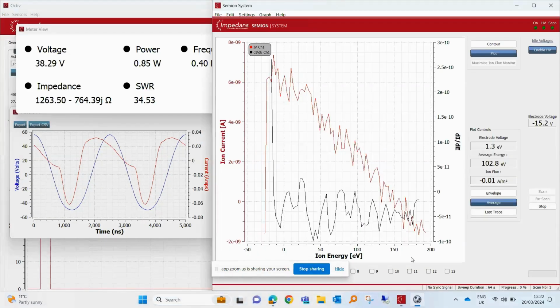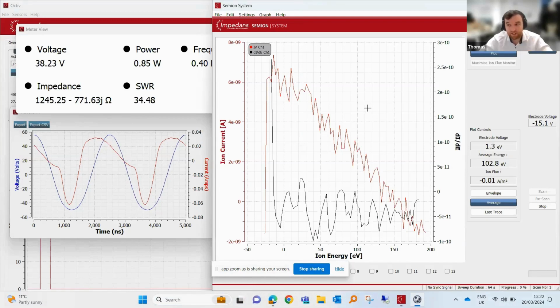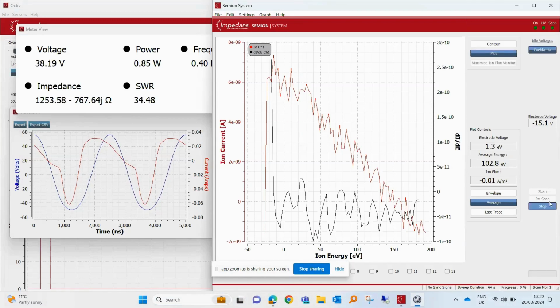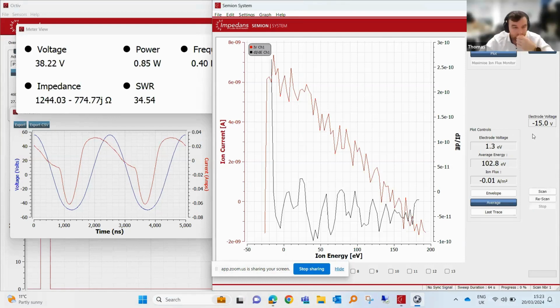So first, we have a 400 kilohertz sine wave onto the bias electrode. Is that where you want to start? Yeah, I'll talk to the group through it. What you're seeing right now, on the left, is the Octiv software. You can see the RMS voltage and the chamber impedance, which is quite high, since we're after the matchbox and using a low frequency. You can see 0.4 megahertz just hidden behind the screen there. So that's 400 kilohertz. And then we're seeing the live waveform.